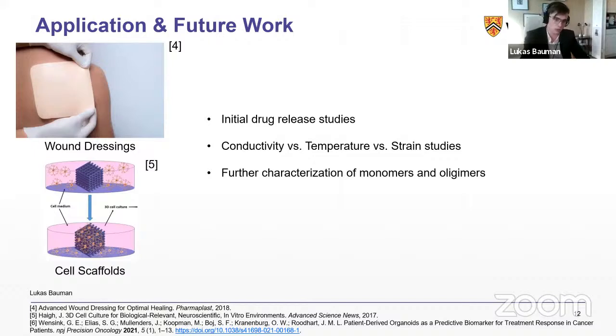In addition to that, we're looking at drug release studies and looking at the conductivity of the hydrogel versus temperature versus strain. So at various temperatures, 4 degrees, 20, and 40, straining it and measuring the conductivity at different strains, because this is a conductive hydrogel as well. And then also further characterization of the monomers and oligomers.